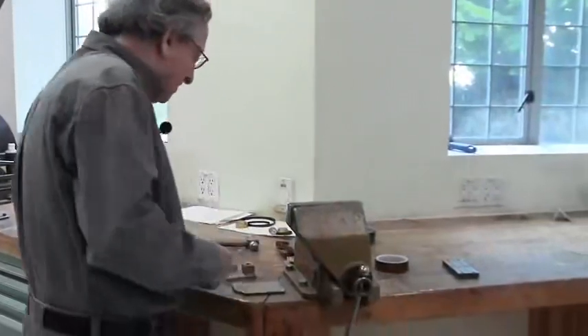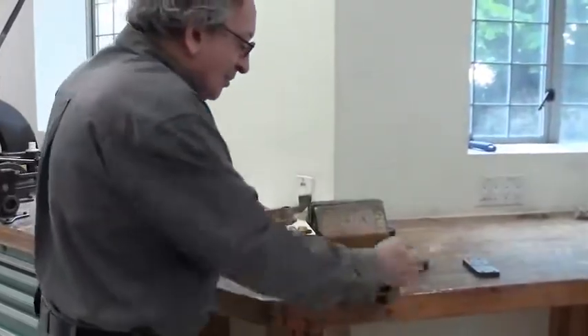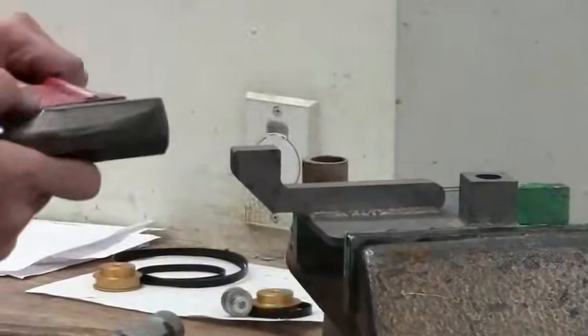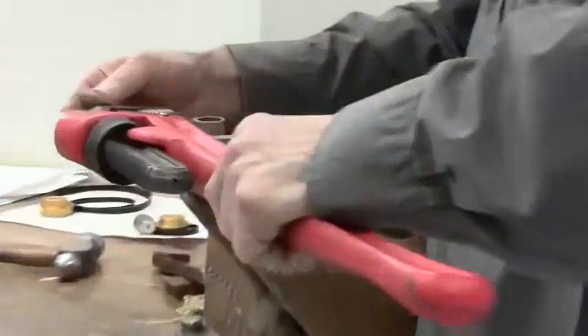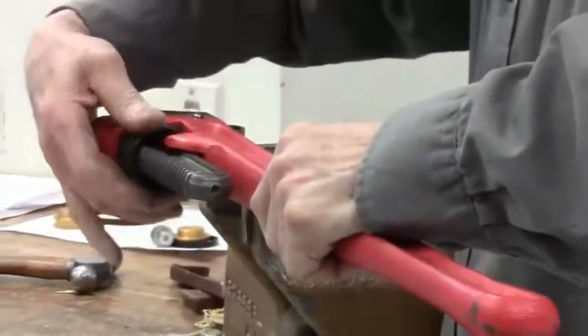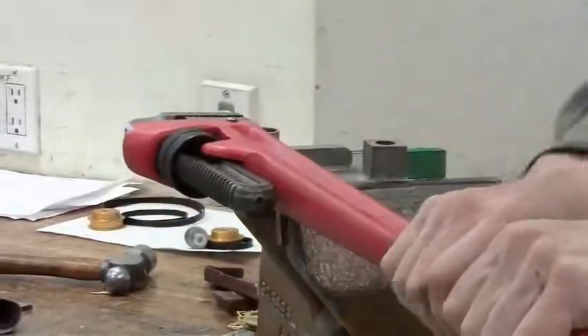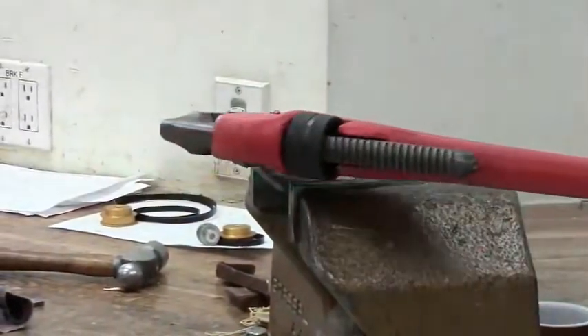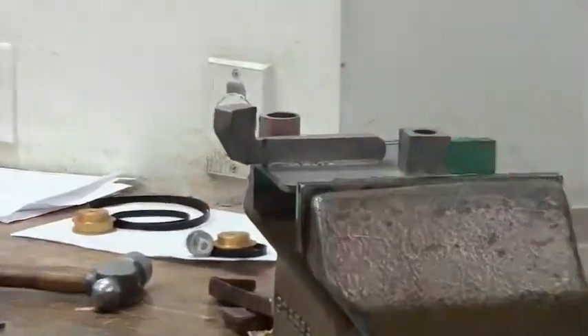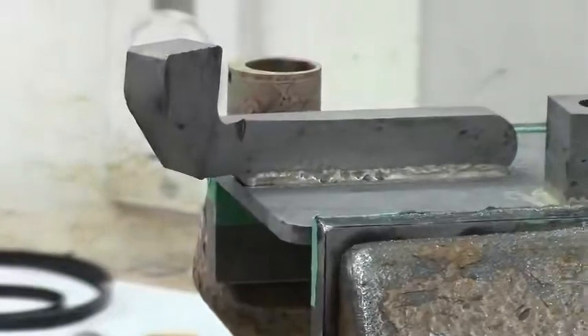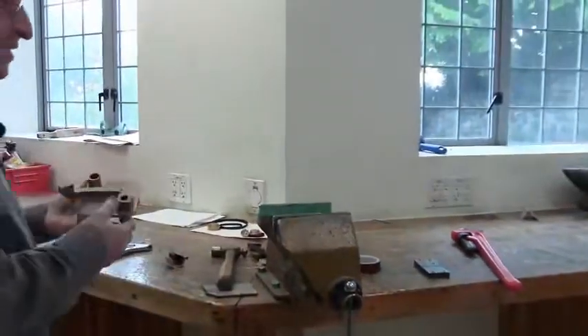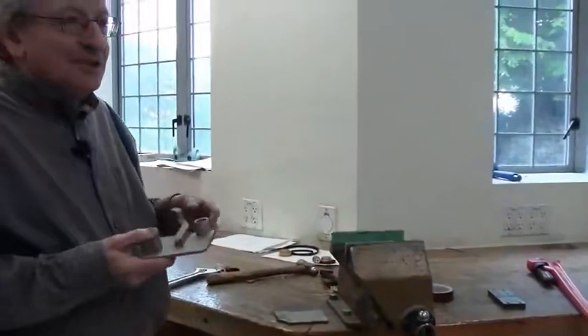On the other hand, if I take the casting built up by brazing, and I do the same test, here I should be able to bend the metal without actually breaking the joint. So let's put on a big wrench on it. Go from here. Like this. So you can see that it's much stronger than casting, both for regular stress and also for hammering. So altogether it looks nicer and it's much stronger and more versatile.